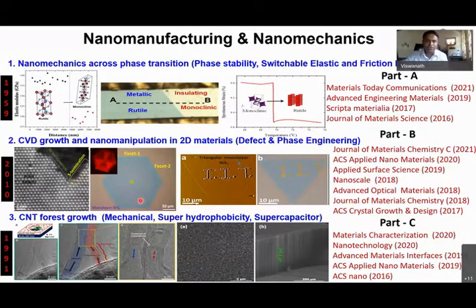I would also like to at least initiate some discussion about 2D materials during the growth, and also with respect to many triggers. It is also possible to induce the phase transformation and also achieve coexisting phases. Especially if you look at this particular image here, it is a fluorescence image. In the optical image, we don't see any contrast, all are uniform. But in fluorescence, you can see there is a dark region and a bright region, more fluorescent and less fluorescent in a triangle form, very nicely self-organized.